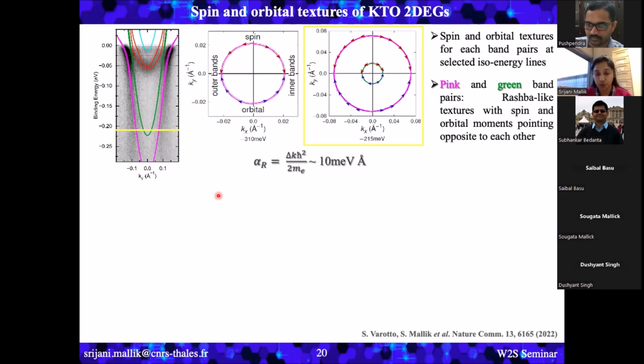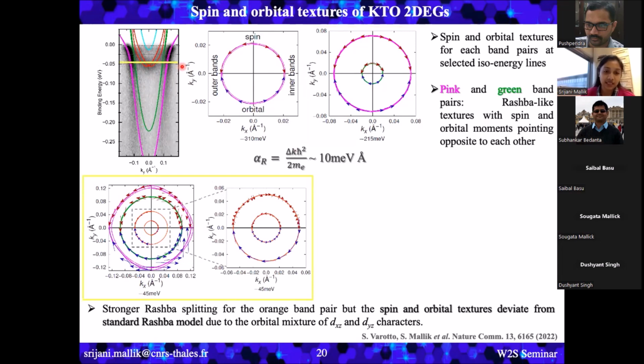So as we move towards this band edge, we can see that this part is the zoom version of the orange band pair. So here we can see that the spin and orbital textures completely deviate from the standard Rashba model due to very high orbital mixture between the dxz and dyz characteristics. So basically what we found from the theoretical calculation is that the signs for dxz and dyz are opposite to each other. And because it's an isotropic structure, it's like a 50%, 50% mixture of dxz, dyz characters. So basically they are canceling each other.